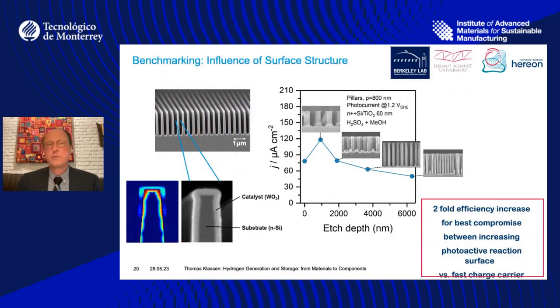So we took a look at the surface structure, different surface structural heights, as you can see here. And you see here the etch depth against the photocurrent, and we can say that a little bit of roughness increases your photocurrent and your efficiency, you absorb more light. But if you go larger than this, then it doesn't help you very much because the charge carriers have to travel all the way along these structures, and that decreases the photocurrent again and increases the inner resistance.